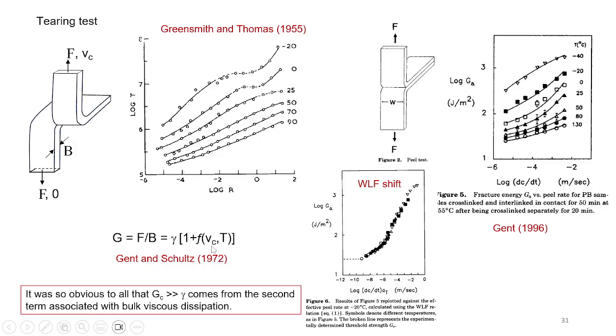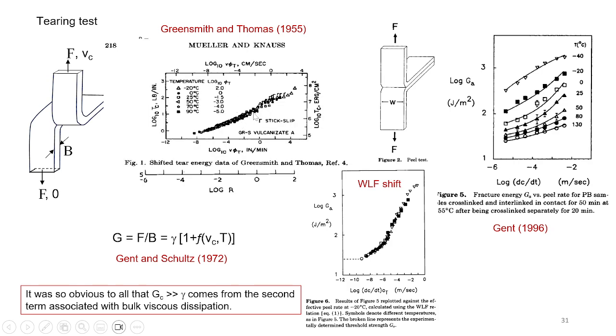So this second term is much larger, which is monotonically changing with the rate, and follows WLF. So that suggests that this is all viscoelastic and viscous dissipation, in fact. So this is the WLF shift here. And there's just tons of work like this. So this is the shift. So they shift it and get this so-called quasi-master curve through WLF.